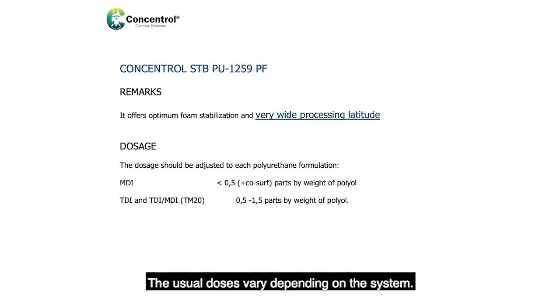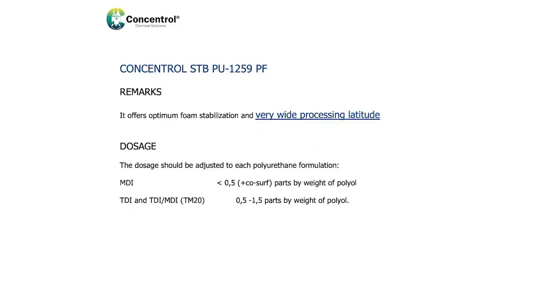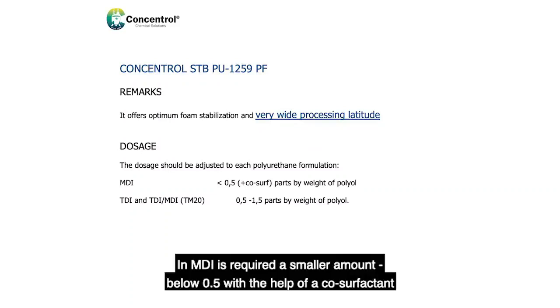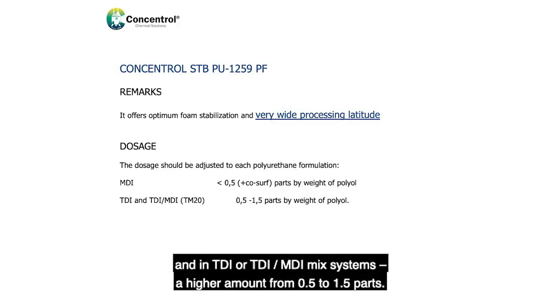The usual doses vary depending on the system. In MDI a small amount is required, below 0.5, with the help of a co-surfactant, and in TDI or TDI-MDI mixed systems a higher amount, from 0.5 to 1.5 parts.